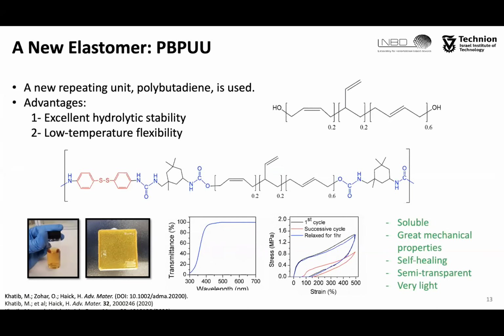In this structure, the polybutadiene parts of the formed elastomer contributed low temperature flexibility and superior water resistance. On the other hand, the 4-aminophenyl disulfide component contributed dynamic disulfide and hydrogen bonds when the urea or urethane linkages were formed.